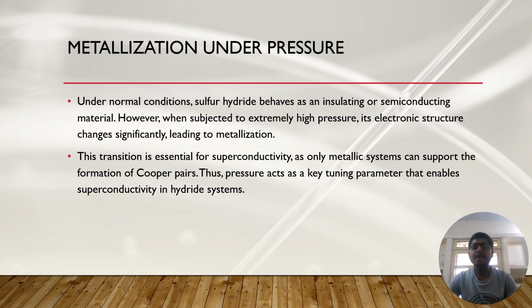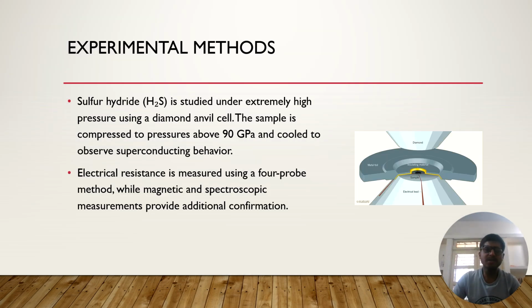Now let us see how this is achieved experimentally. To achieve such extreme pressures, a device known as a diamond anvil cell is used. In this setup, a very small sample of sulfur hydride is placed between the flat tips of two opposing diamonds. By applying force, pressure exceeding 100 gigapascals can be generated, which is comparable to the pressures found deep inside the Earth. Diamonds are used not only because of their exceptional hardness but also because they are transparent, allowing optical and spectroscopic measurements to be performed during the experiment.